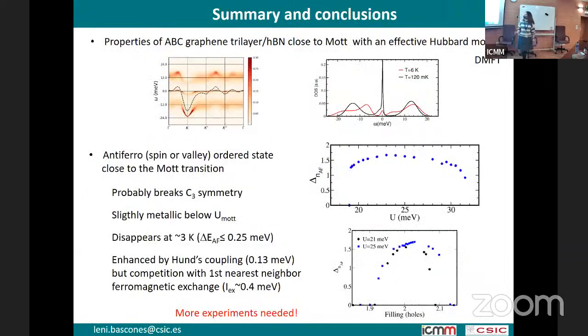So okay, let me just summarize. We have seen that if we are talking about Mott physics, we really expect unconventional behavior. So we should not expect well-defined bands, particularly when we are really at the insulating state. But we can go beyond at temperatures above the ordering phase transitions, look at temperature dependencies, look at doping dependencies, because we should find anomalies. This is the way in which we should look at the nature of the system, to verify it, or the opposite, to say that this is not happening.